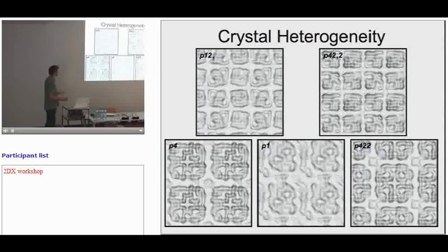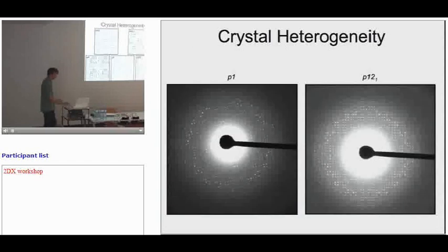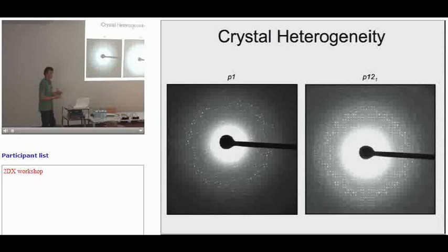I took images, and these were all just vastly different ways that, because it's a two-layer crystal, the two different crystal layers can come together. And since even the untilted diffractions you couldn't segregate, if you have unit cells that are quite different, you can use untilted diffraction patterns to discriminate. But because these were almost identical regardless of which crystal form, I couldn't segregate just on the basis of the untilted diffractions. So what I had to do was use a method that Fujiyoshi's lab first used with aquaporin 4,